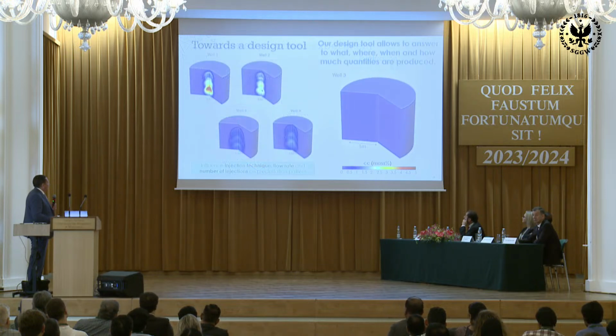Second and last case, for instance, we look at a single well. In this case, we are in partially saturated condition with the traditional MICP. And again, here we look at different configurations to optimize the process. And we do it numerically now because we don't need to have this parametric analysis done experimentally, because we have confidence in the model and we see how much calcite we can get. An important aspect here is that we can control and manage the calcite. So we don't need to work all the time with the same calcite values, and then we come back to this.